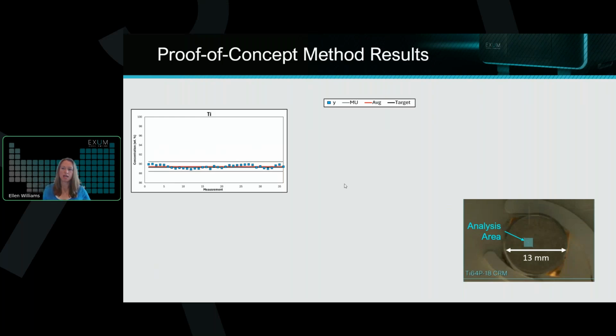So what you see here is once we developed that method, we then repeated the same method 36 times over multiple months, over multiple instruments and multiple users in order to get the data blocks that you see on that graph. So we're first just looking at titanium while I orient you on the data that we're presenting here on the results. You can see all of those measurements from 1 to 36 shown in blue, the average of all of those measurements shown in red compared to the target number based on the known results from that reference material that we had. We also statistically determined the measurement uncertainty, which is what you see as those gray bands there, just based on the variance that we saw in the measurements.